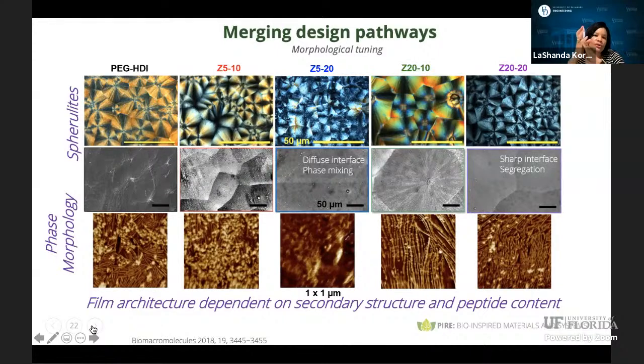So if you look at our control, you can see really nice Maltese cross patterns in the polarizing optical micrographs at the top. You can see in our SEM that you have really nice spherulitic structures with different types of grain boundaries, interfacial interactions, and really nice fibrillar structures. For the Z510, they are similar in structure to our control in terms of the spherulites, Maltese cross patterns, and the size of the crystallites, and you can start to see really nice interfaces emerge and nice fibrillar structures.